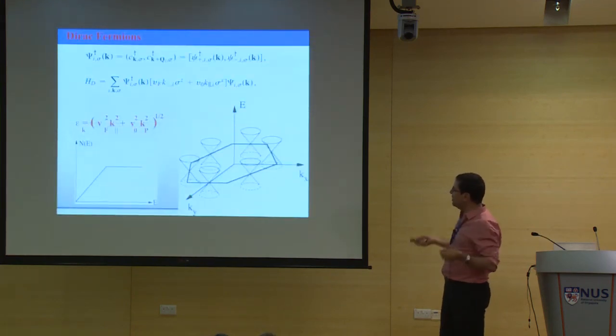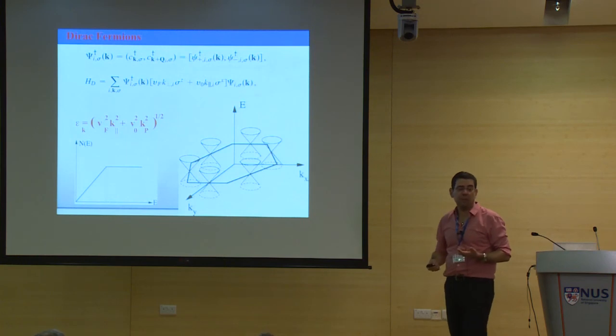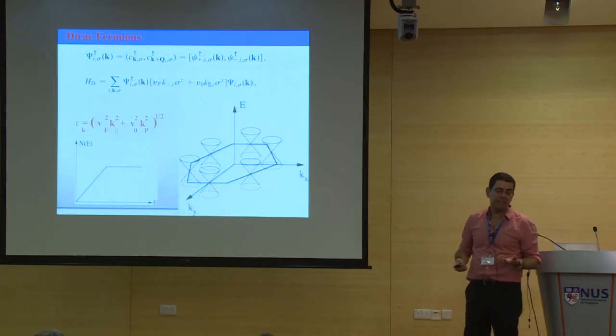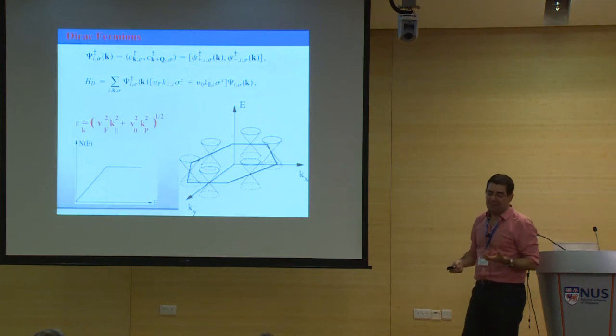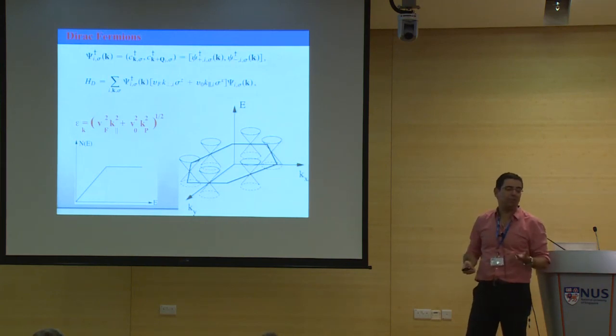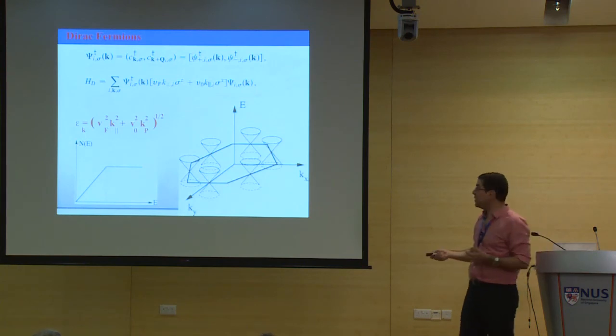Okay, so this was the proposal. This is the Fermi surface. So you have all these Dirac cones there. And we all know what happens if you have Dirac electrons. I didn't know at the time. This was pre-graphene for me. The density of states is linear in energy if you have Dirac particles. And now you have to explain how can superconductivity be born out of something which has a reduced density of states. Okay? Again, these many-body states use the energy from the density of states for condensation. So you have to explain that.